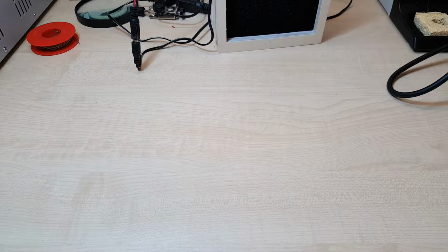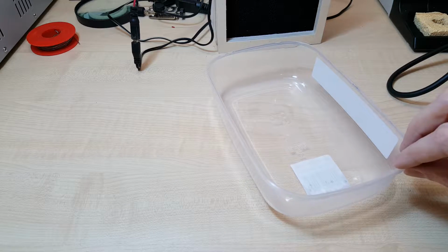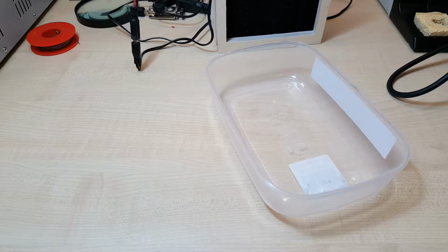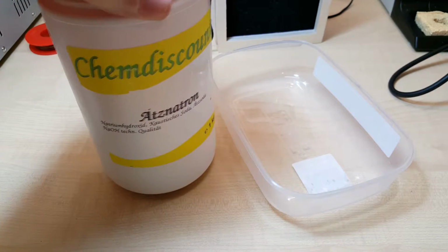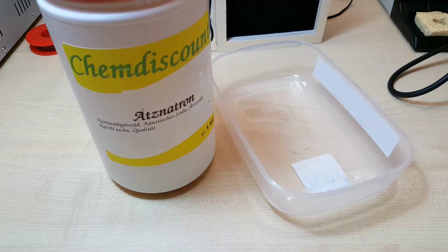Okay, so now before we begin to expose the PCB to the UV light, we need to set up the developer for the PCB. That is quite easy. You just need another container and sodium hydroxide. You need about 15 grams per liter.